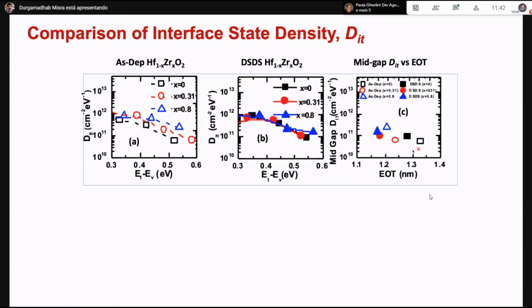That we also showed. If you look at the silicon band gap in this figure, you can see the interface state density actually goes down for the DSDS sample with hafnium zirconium percentage. Both in the 31% and 80% cases, it went down. This goes along with the EOT, because once we reduce the EOT, at the same time we should make sure the Dit also goes down.